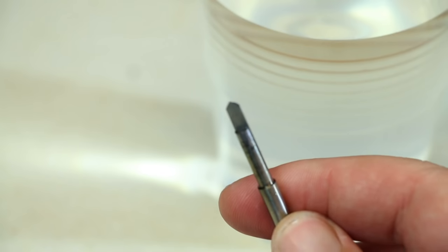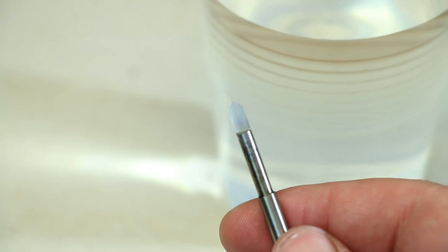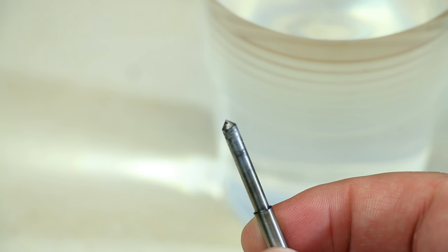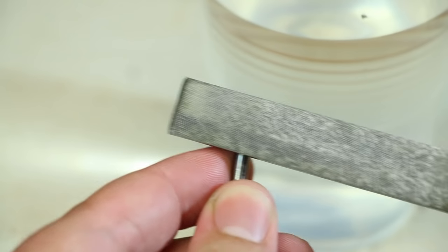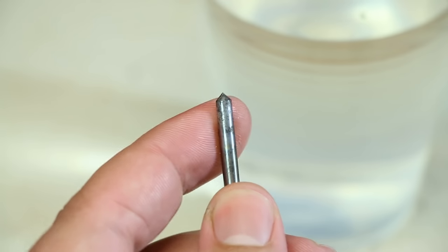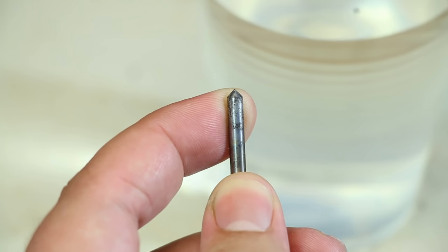As you can see, there is minimal scale on the flat surface where the boric acid powder was concentrated on. And we reduced the black scale on the rest of the tool. To test if the hardening process has worked, we run an old file over the tool. The file shouldn't scratch the surface as the workpiece will now be harder than the file.